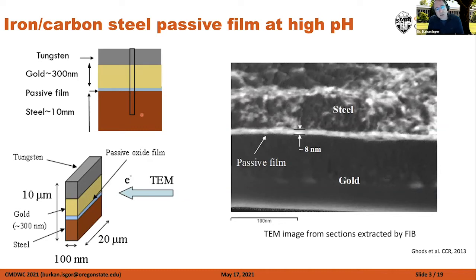From time to time, you can take those specimens out in a nitrogen purge or argon purge environment, sputter some gold and tungsten on it, and then you can do focused ion beam milling to extract samples like this, cross sections. The idea here is to create electron transparent cross sections so that you can look at them from the side using TEM. The idea is to see this thin passive film and characterize it if possible. These FIB samples are about 100 nanometers thin, and if you look at those images, you can actually clearly see the passive film.